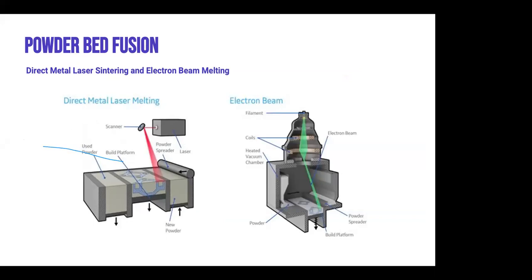SLM and DMLS, both selective laser melting and direct metal laser sintering, produce parts via methods similar to SLS. The main difference is that SLM and DMLS are used in the production of metal parts. SLM achieves a full melt of the powder, while DMLS heats the powder to a near melting temperature until they are chemically fused together. DMLS works with alloys, while SLM can use single component metals such as aluminum. Unlike the SLS process, SLM and DMLS require support structures to compensate for the high residual thermal stresses generated during the printing process.